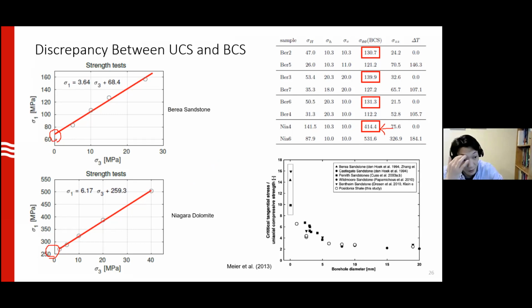It turns out this is somewhat a known effect. It has been understood that the strength of borehole walls becomes stronger as the borehole gets smaller. You can understand this as a typical size effect that's empirically known. Some have also tried to use fracture mechanics to explain this, but the essence is that even for boreholes that are 2 centimeters in diameter, the critical tangential strength, that's the hoop stress at failure, divided by the uniaxial compressive strength, is about a factor of 2. So we are not 100% comfortable with this discrepancy, but if we can say that this is a known effect, and that these numbers we recover from the experiments represent the strength of the borehole, we can apply this number when we do a heated experiment.